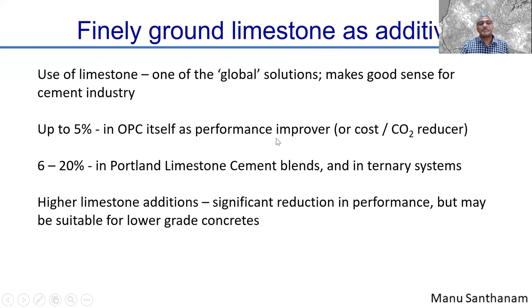We call it a performance improver. So in reality, what it's doing is it is reducing the cost, and it is also reducing the total CO2 emitted from your cement. Per bag of cement, you are reducing the cement quantity or clinker quantity and replacing it partly with limestone. So you have actually reduced the CO2 impact of the cement.